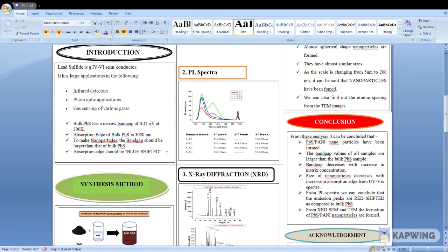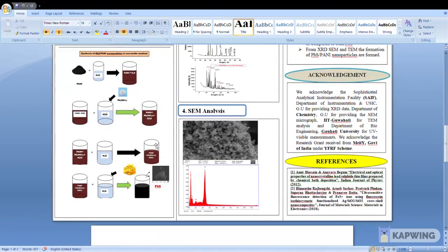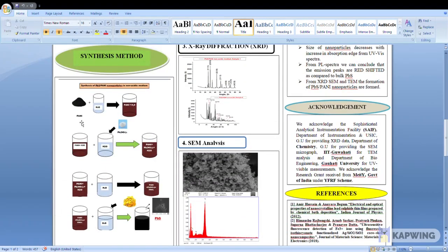The synthesis method. For synthesizing lead sulfide nanoparticles, we have taken PANI, which is polyaniline, by polymerization reaction. We have added water to PANI and then we have added lead nitrate solution to it. After adding lead nitrate, we stir it for 3 hours. After that, we have added sodium sulfide dropwise, and finally the lead sulfide nanoparticles are formed.